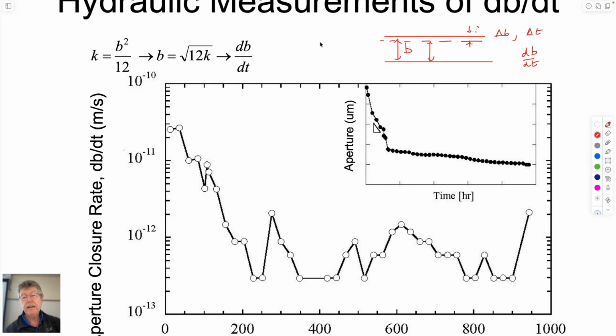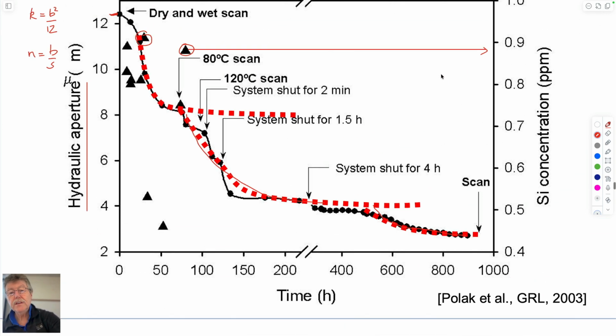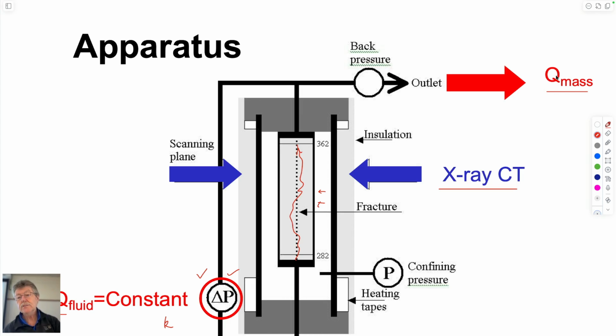But also, you'd expect that this db/dt, if you multiply this aperture change by the density of the dissolved mineral, so if this is being dissolved, you'd expect it to go the other way. If this is mineral material that's being removed, then the mass of that mineral would give you, if you sum it up over the whole fracture, a mass concentration that comes out of the fracture. So the idea is that if you measure both the dissolved mass concentration coming out and the volumetric flow rate, Q, flow coming out, this gives you an idea of the change in aperture through the mass balance in the fracture of the dissolved mineral, and this gives you something about the fracture measured from the flow field.